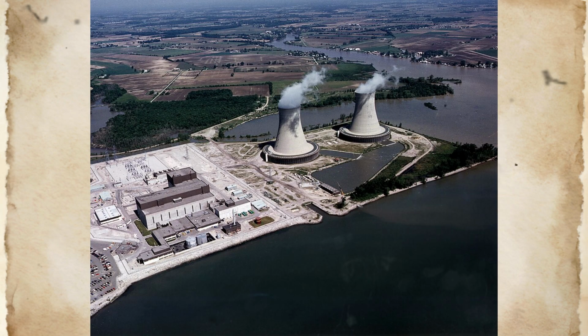A third fuel assembly showed evidence of severe thermal exposure with extensive fuel pin damage but no complete fuel melting, indicating that it had experienced significant flow blockage for a shorter duration or to a lesser degree than the two assemblies with complete fuel melting. The damage pattern within this assembly was consistent with partial flow blockage that had caused fuel temperatures to approach but not exceed the melting point of metallic uranium, before reactor shutdown terminated heat generation and allowed thermal recovery.